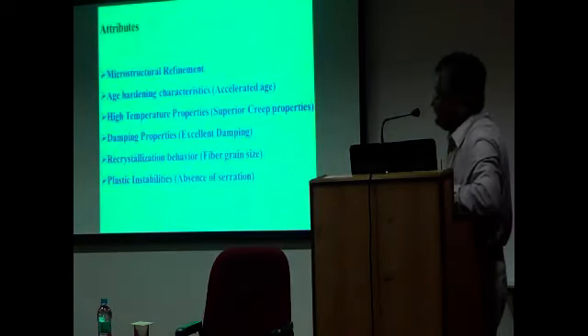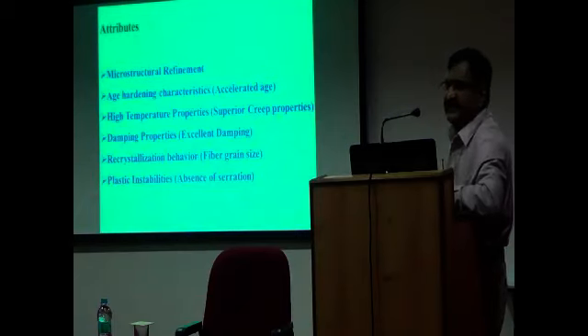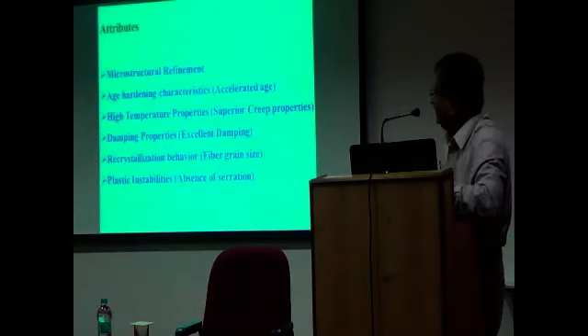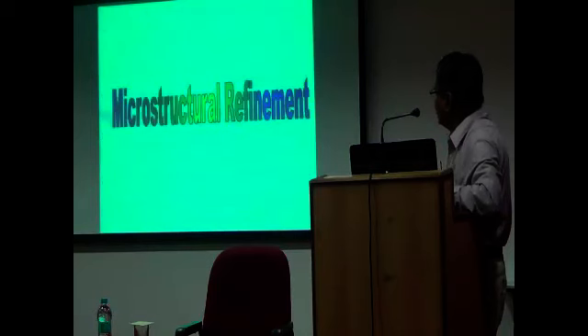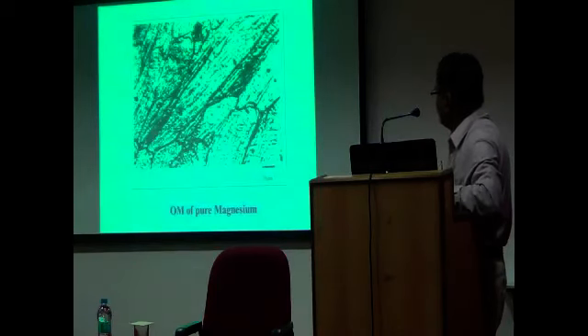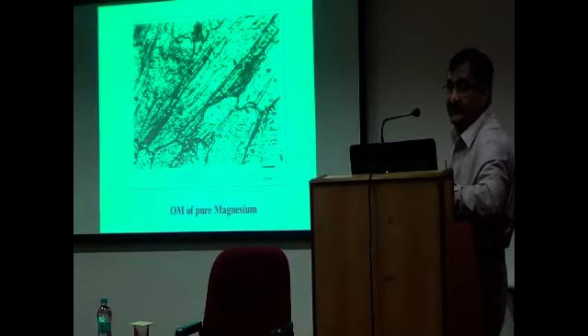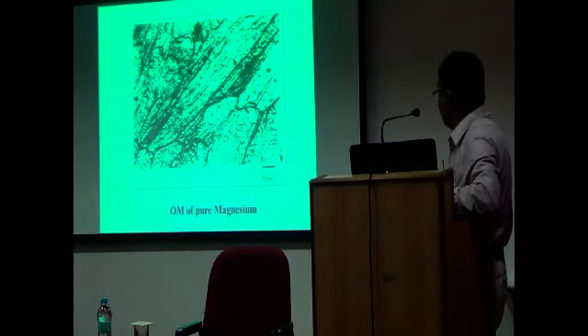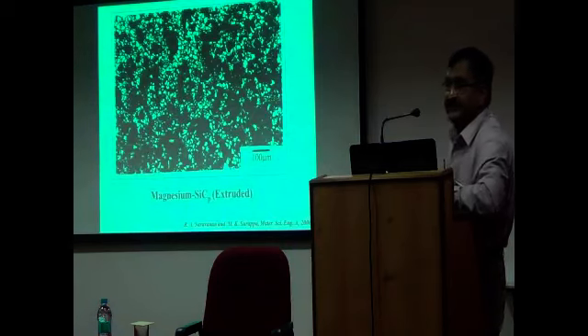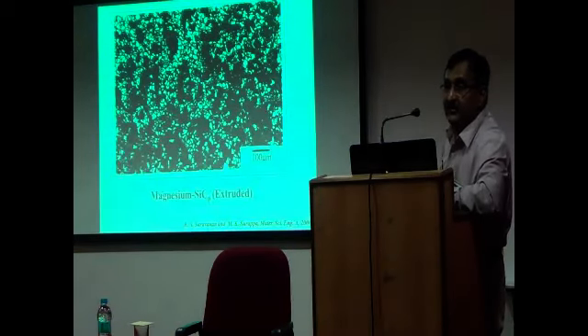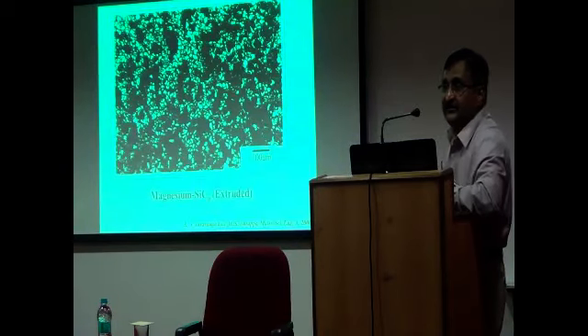And when you have these particles, there are various intrinsic changes in the properties: grain refinement, age hardening characteristics, high temperature properties, damping properties. Various things will change substantially. For example, I just wanted to show you this pure magnesium. You can see the very large grain size. When you add silicon carbide to this, you can see how fine a grain size you get. So in addition to the particle, the grain size changes, and when grain size changes, properties change.